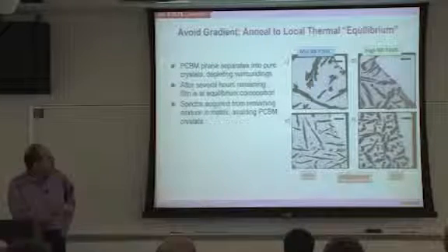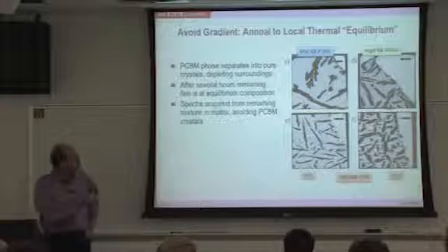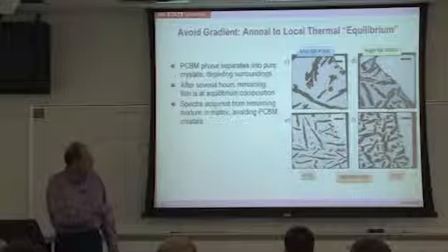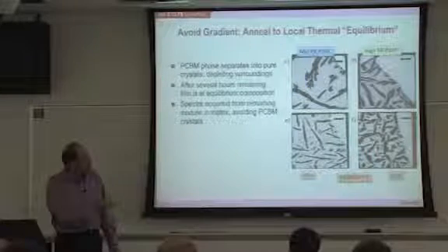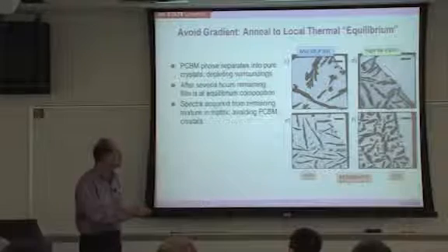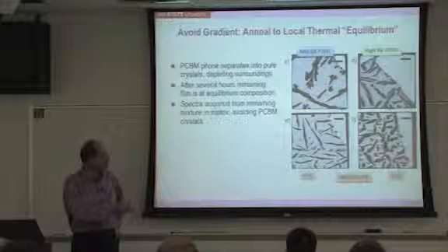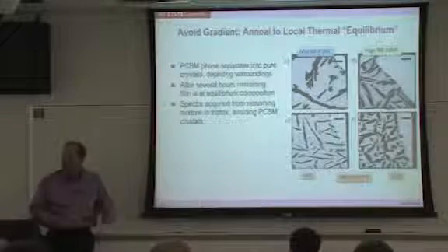Again, two systems here. P3HT of different regioregularity, and then the bottom is PPV with different ratios of the fullerene to polymer. And so as we add more fullerene, of course, we deplete that more into these crystals. So this is a visual representation too: you deplete all the fullerenes, and we measure the matrix here and essentially get the same value. So that is one way of checking that we measure a thermodynamic quantity here.